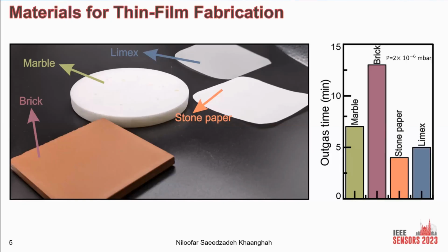Here you see all the stone-based substrates that we load in the sputtering vacuum tool to check their outgassing time. As you see here, for all the substrate materials to reach the pressure of 2 × 10^-6 millibar, the outgassing time took less than 15 minutes for all the substrates, which is quite manageable in a short time.